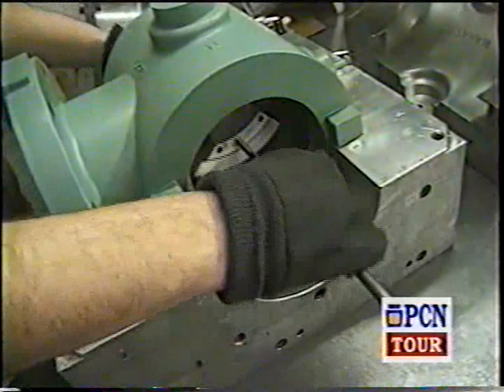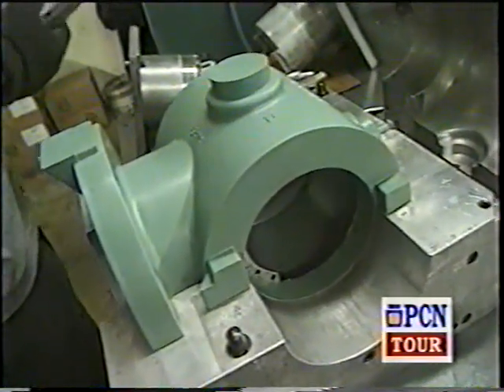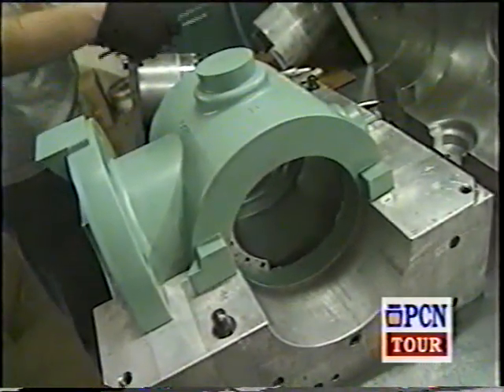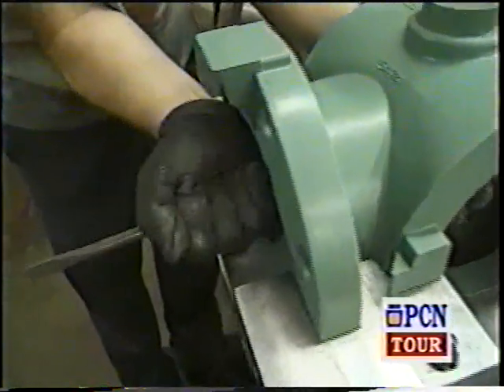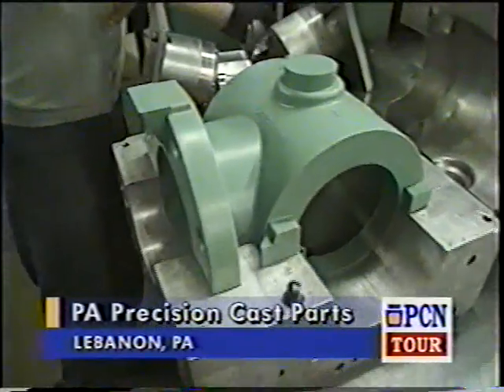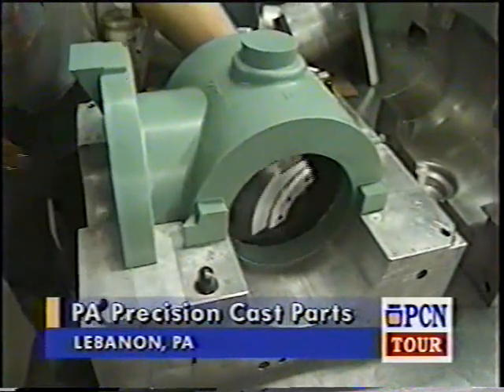One of the interesting things about wax is that as it solidifies or freezes, it shrinks. We all think of water as it freezes, it expands. Wax is different. Most liquids shrink as opposed to expand when they freeze. Therefore, to hit the proper dimensions of any tool, the tool must be built with the shrink factors in mind.